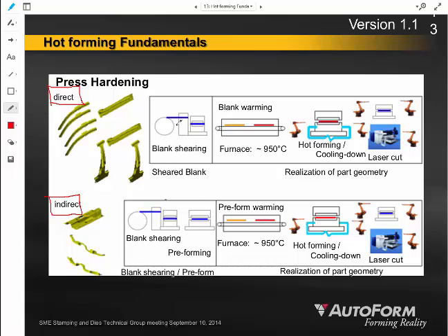Direct hot forming starts by taking the coil of material, unrolling it, creating your blank, taking that flat blank and passing it through a furnace to heat it up very uniformly to a temperature around 950 degrees Celsius, loading it into the stamping die, and inside of the die not only deforming the material, but as we're deforming it, also cool it and quench it down to ambient temperature, right?